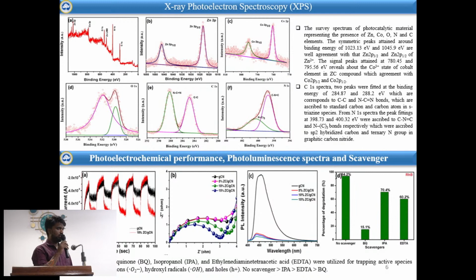So through this we can conclude that the highest degradation has been obtained with respect to BQ, because a scavenger is an inverse of percentage. If we are getting a lower percentage in the particular sample, it retards the functioning of superoxide radicals, which shows the highest participation of radicals in the degradation process. So we obtain only a lesser degradation with the scavenger analysis. We have confirmed from this test that the superoxide formation, carried out in the conduction band of the material, has made the highest participation in the degradation process.